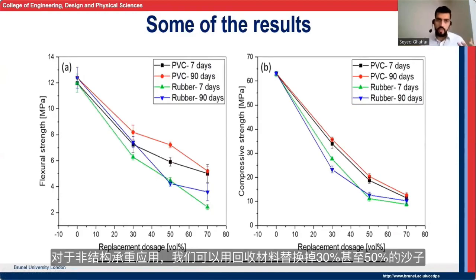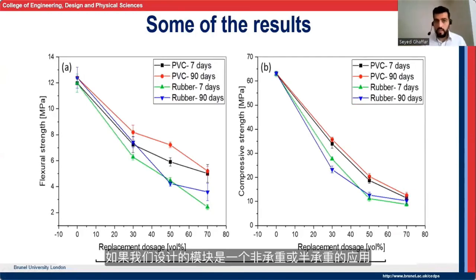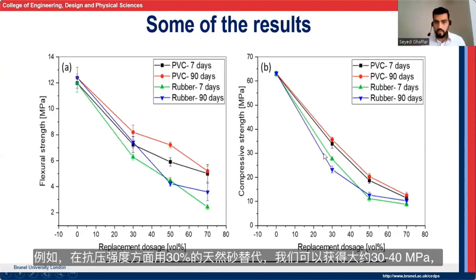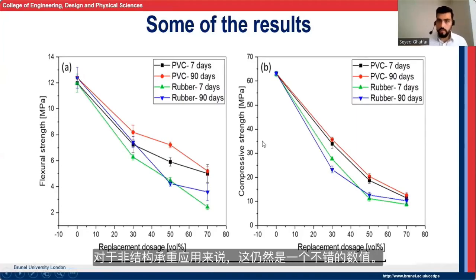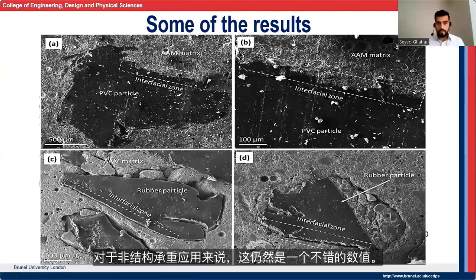And we can actually, for non-structural load-bearing applications, replace up to 30% or even 50% of the sand with recycled materials if the application that we are designing for is a non-structural or semi-load-bearing application. Because for example, for compressive strength, at 30% replacement of natural sand, we were able to get around 30 to 40 MPa, which is still a respectable value for non-structural load-bearing applications.